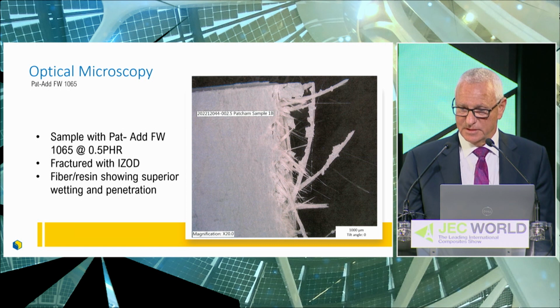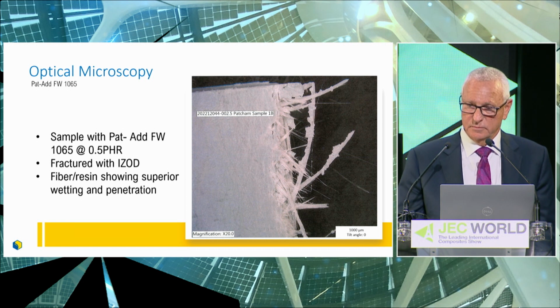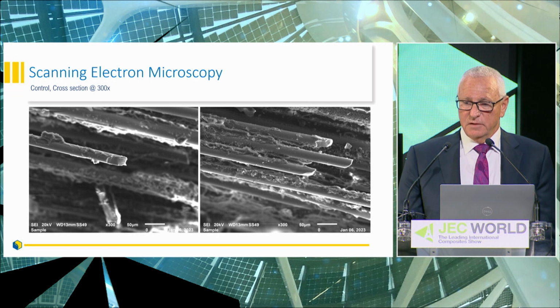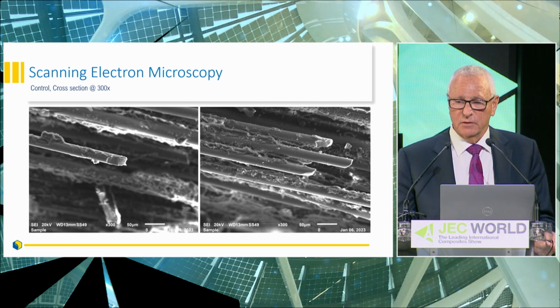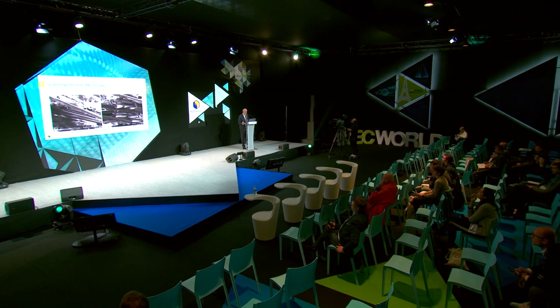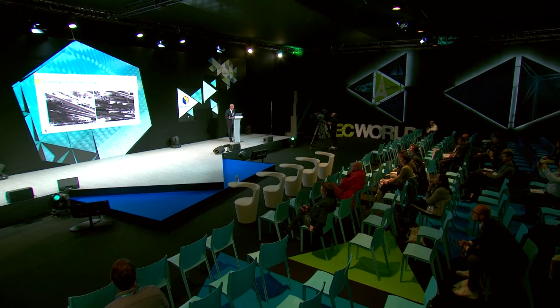And this is 20 times on an optical. On the scanning electron, when we went to 300 times, we're looking at single fibers. And again, this is the control. So keep that picture in your mind when we go to this one. And that's no cheating here. It's exactly the same magnification, and you'll see the fibers are much more swollen and much better surrounded, indicating complete penetration of the fibers using the additive. Again, this is the FW 1065 at 0.5 parts per 100 resin.